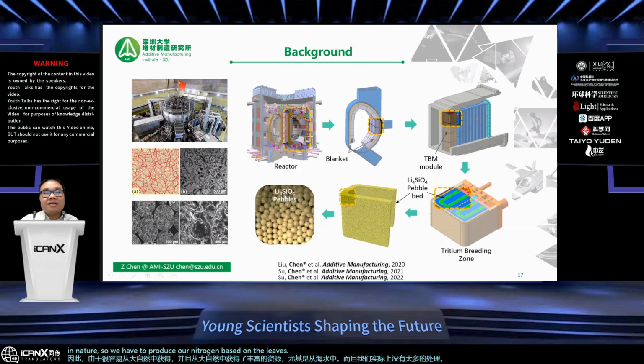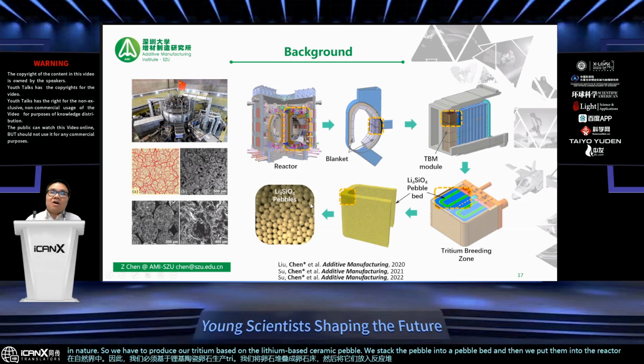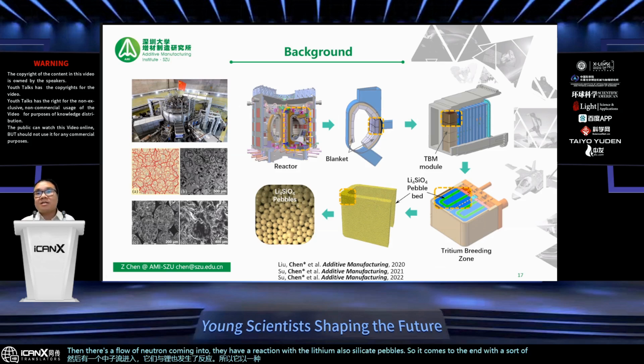And we don't have too much tritium in nature, so we have to produce our tritium based on lithium-based ceramic pebbles. We stack the pebbles into a pebble bed, and then we put them into the reactor. Then a flow of neutrons comes in and reacts with the lithium silicate pebbles, ending with the generation of tritium. So we call this a tritium breeding zone. Tritium breeding means that we produce tritium from that kind of facility.